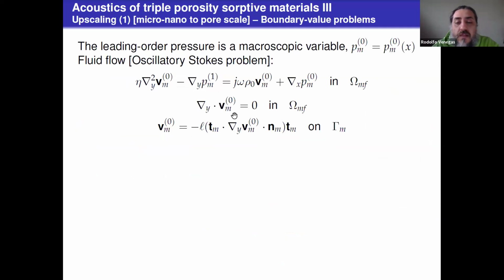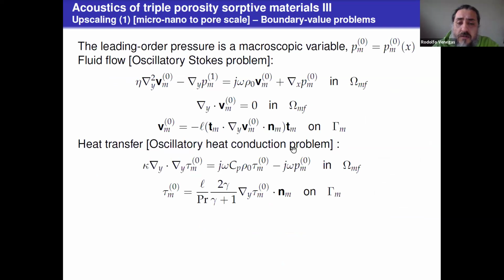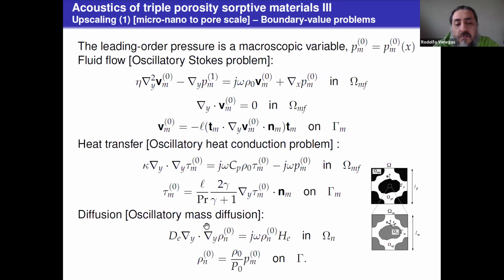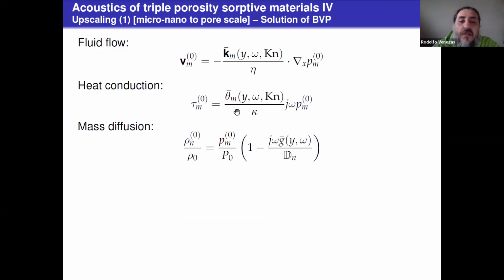So applying homogenization, we identify different problems. This is a Stokes problem with a slip boundary condition, an oscillatory heat conduction problem accounting for rarefaction effects through this temperature jump condition, and also the mass diffusion problem with a force density on gamma, meaning that the pressure here is forcing this diffusion to happen in this domain. So these are three linear problems. The solutions can be written as operators acting on the forcing terms: fluid flow with respect to the gradient of pressure, heat conduction with pressure, and mass diffusion also with pressure.